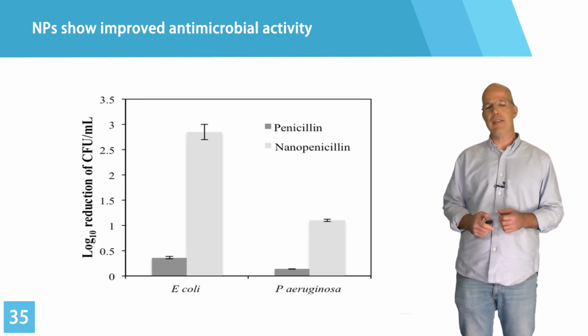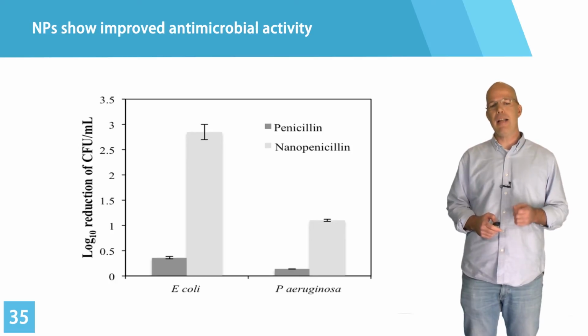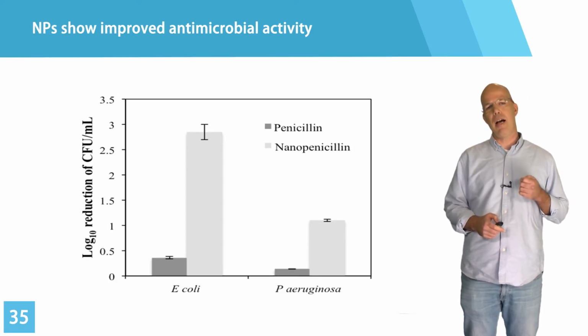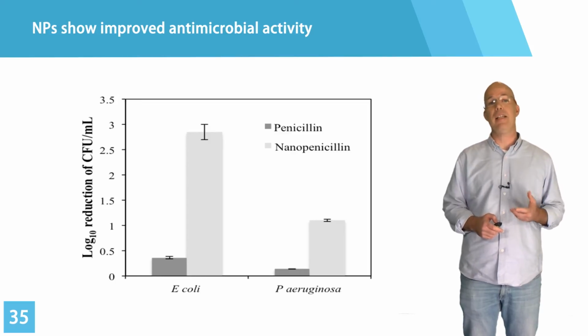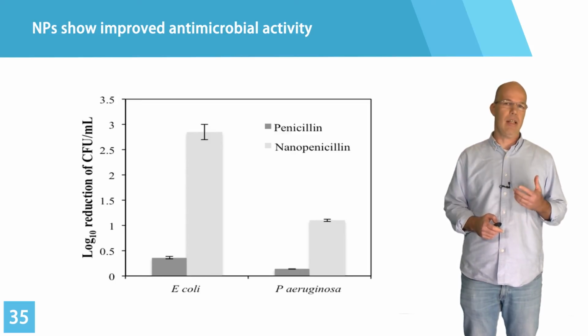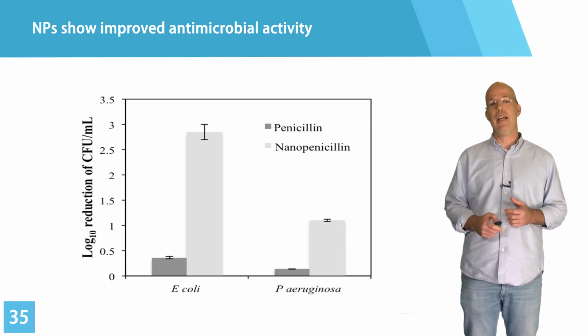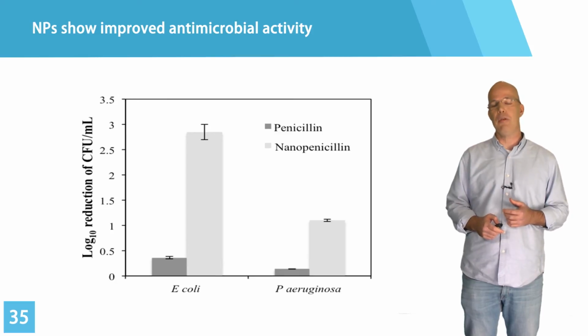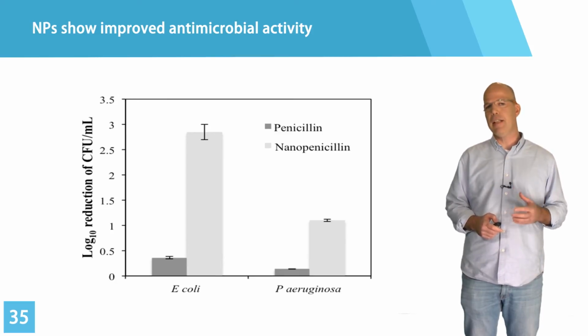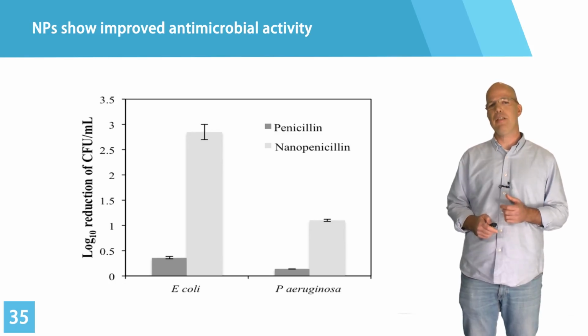So what you can actually see here is how nanospheres of penicillin are more active than the pristine penicillin solution, the same antibiotic that Fleming discovered almost 90 years ago. And you can clearly see that once we use the nanosphere, the nanopenicillin, the activity is much higher.